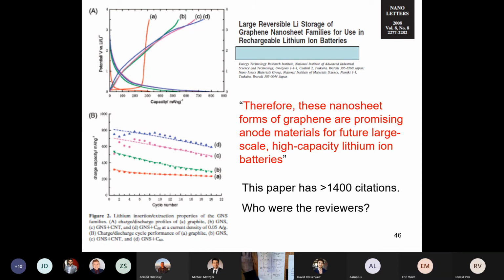Yeah, and think about the energy hysteresis, right? You'd be charging the cell between 4 volts for the positive, and then this is the curve the negative follows during charge. It'd be 4 volts during charge and 2 volts during discharge. The thing is 50% energy efficient. Total garbage. Got it. Okay, cool. Any other questions?